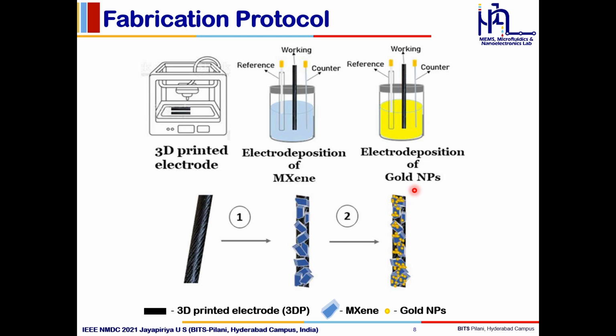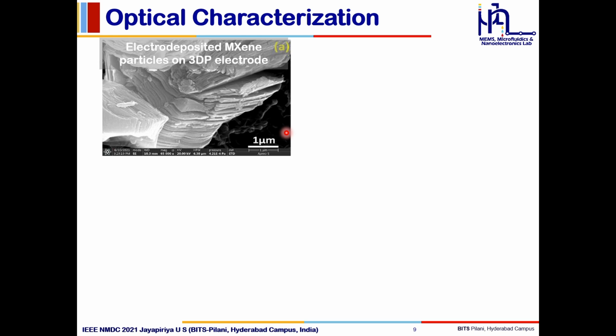In this work, we will be talking about 3D printing and the electrodeposition of 2D materials and gold nanoparticles. First, commercially available graphene filament was used for making the 3D printed electrode with required dimensions. The next step was electrodeposition of MXene. MXene has been attracting huge attention because of its high electrical conductivity with an added advantage of highly hydrophilic surfaces. After the electrodeposition of MXene, gold nanoparticles were also electrodeposited over these MXene coated 3D printed electrodes.